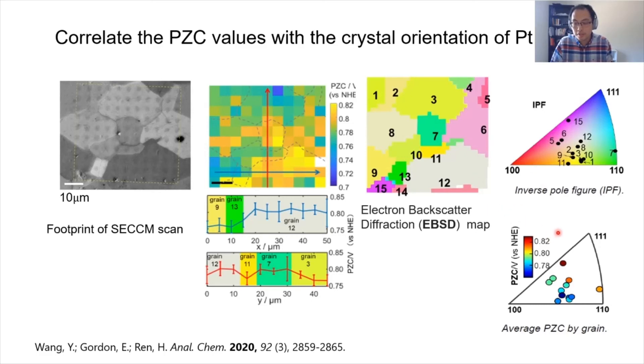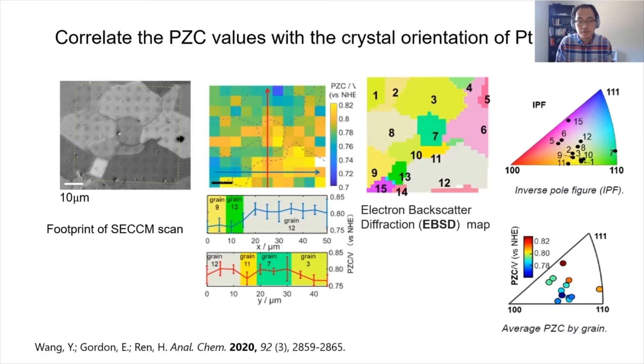We find that on average, if the grain is closer to the (111) orientation, the PZC value is going to be larger. If the grain is closer to (100) or (110), the PZC value of platinum is going to be more negative. This is consistent with measurements on single crystal electrodes.